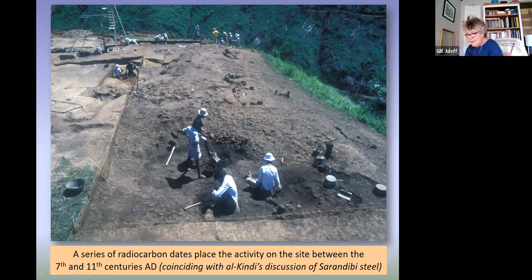What's important is that we have a series of radiocarbon dates from this site, and they date the activity on this site to between the 7th and the 11th centuries. Interestingly, coinciding with the date of Al-Kindi's treatise on swords and iron, where he discusses Sarandibi steel. So these dates coincide. On this site, we excavated something like 41 separate furnaces, and we only excavated less than 20% of this site. So there's an enormous amount of production and industry here.